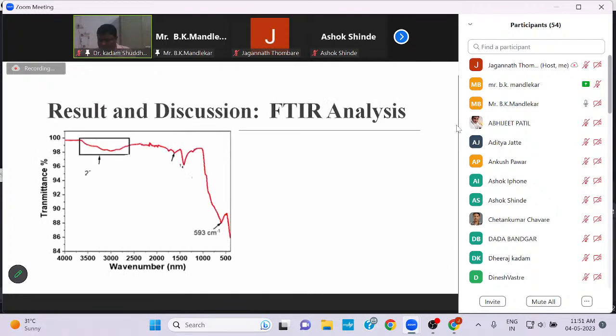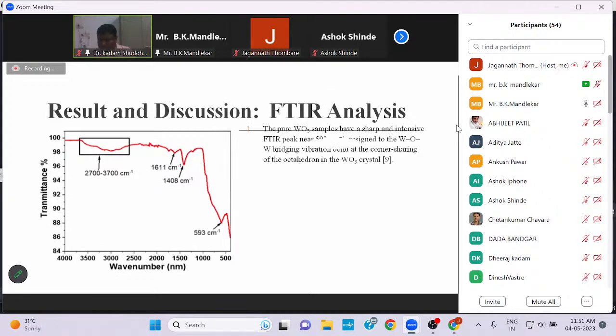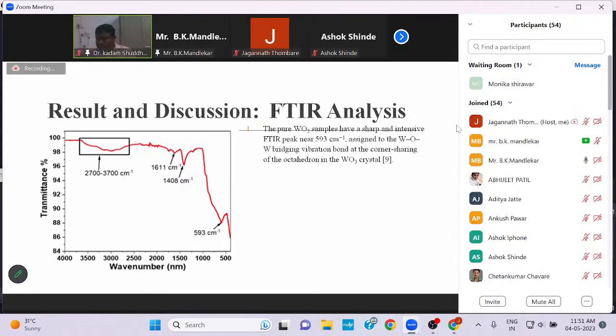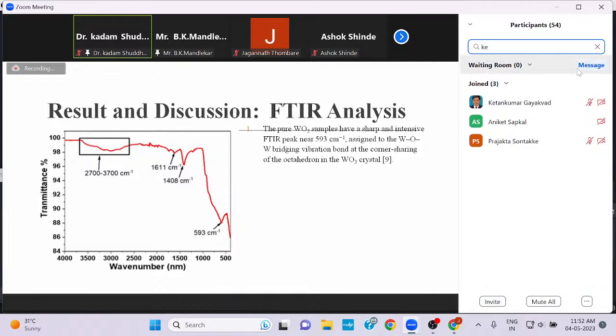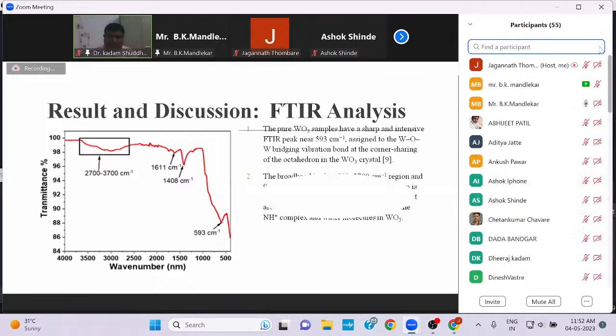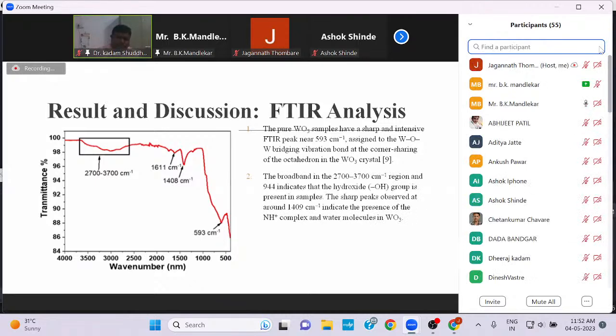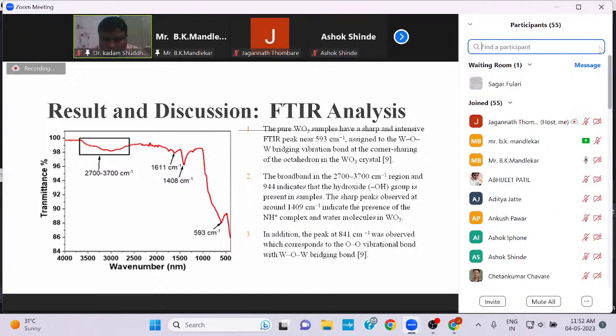We have also done FTIR analysis. In FTIR analysis, we got the graph that pure WO3 samples have sharp, intense peaks near 593, assigned to tungsten-oxygen-tungsten bridging vibration at corner-sharing of octahedra in the WO3 crystal. The broad band in the 2700 to 3700 region indicates that hydroxide OH groups are present in the sample. The sharp peak observed around 1409 indicates the presence of ammonia complex, since we have added ammonia, and water molecules in the liquid. In addition, another peak was also observed, corresponding to a vibration.